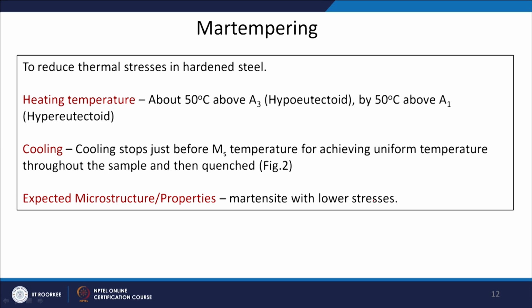Sometimes when you do this kind of very fast cooling, martensite itself is hard and brittle. On top of that, you also have these thermal stresses which can introduce some cracks in the material even before any stresses are applied. So that we don't want. So we can reduce the thermal stresses by doing a mar tempering operation.